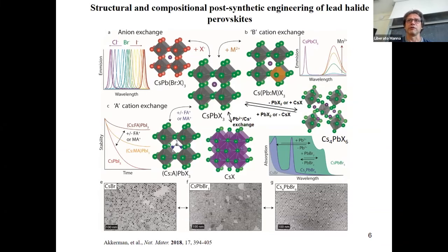Here you see a panel of all the possible types of transformations that you can do on perovskite nanocrystals. You can do anion exchange, and so tune the band gap. You can do B-cation exchange, and so, for example, dope nanocrystals with manganese and get also orange emission. You can change the A cation, and so stabilize or destabilize the nanocrystal structure, and also change a little bit the band gap. And you can do also all these transformative reactions in which, for example, lead bromide or cesium bromide is inserted or extracted from the nanocrystals, and you can go all the way from, for example, cesium bromide to cesium lead bromide to Cs4PbBr6.